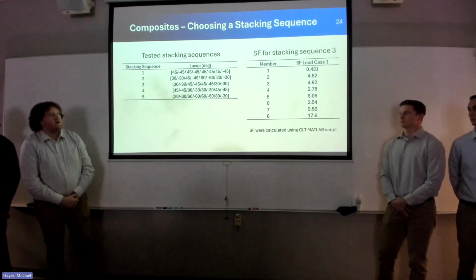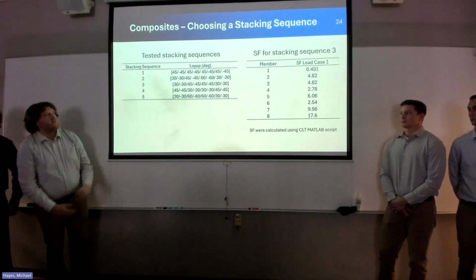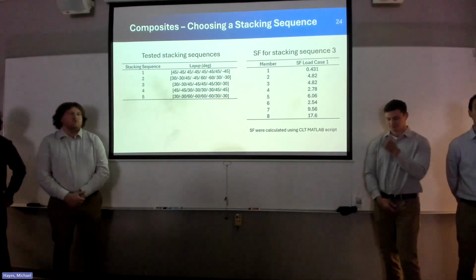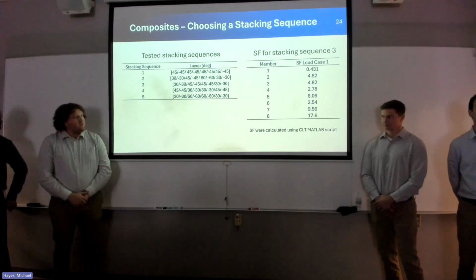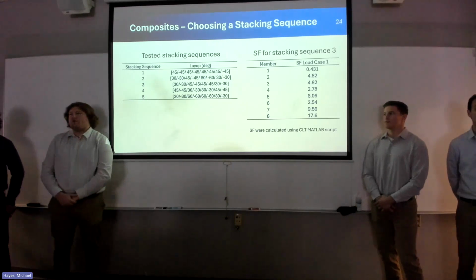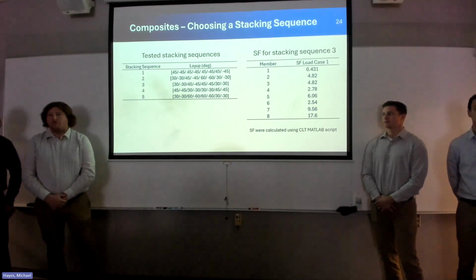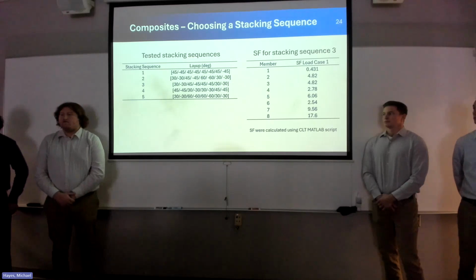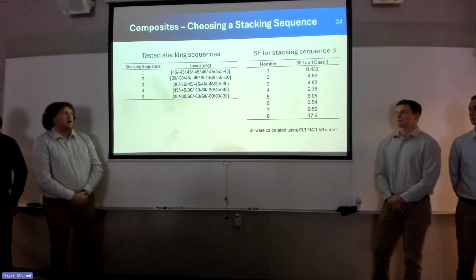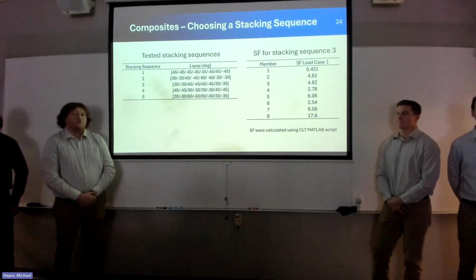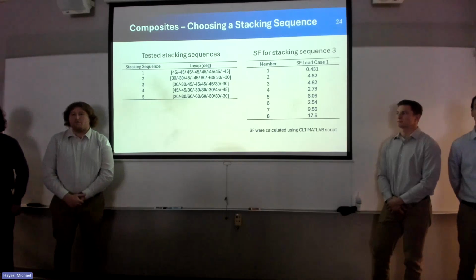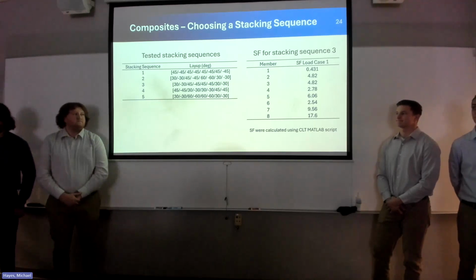The only member that did not pass on any of the stacking sequences was member 1, that structural important bar. And in order to get that to a minimum factor of safety of 1.5, I did have to double the stacking sequence, which is in essence doubling the wall thickness of the tube. I think this massive discrepancy is due to the classical lamination theory assumptions that we're making for tubes.